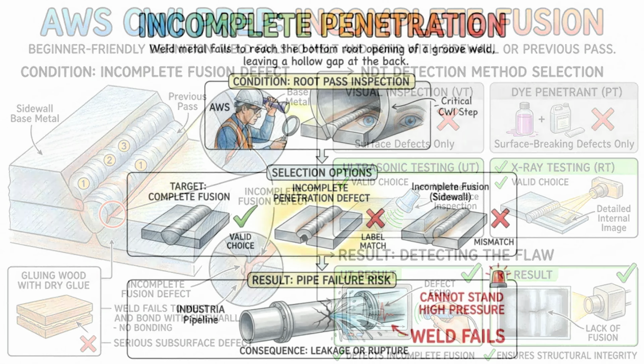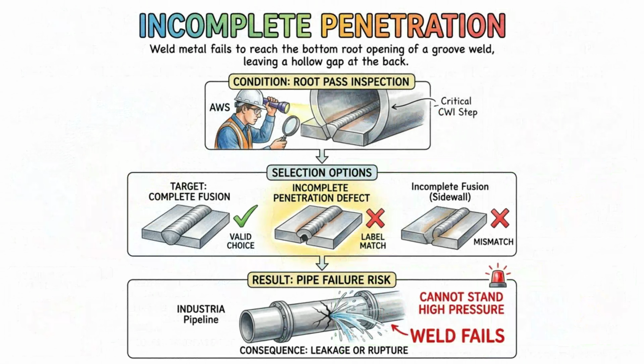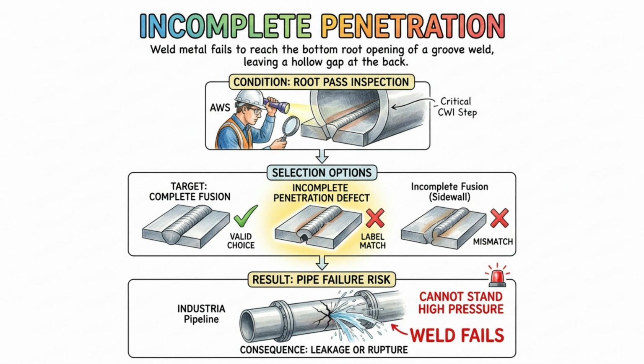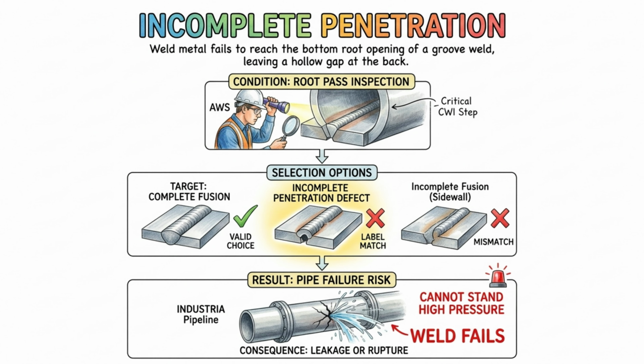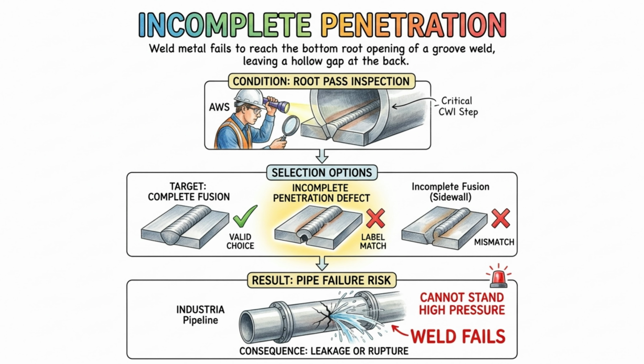Incomplete penetration is closely related to fusion problems, but it specifically occurs at the very root of the joint. This defect happens when the weld metal fails to completely reach the bottom root opening of a groove weld, leaving a hollow gap at the back. If a pipe joint has incomplete penetration, it cannot withstand high internal fluid pressure and will eventually leak or rupture. Catching this during root pass inspection is a crucial responsibility for any inspector working on industrial piping systems.